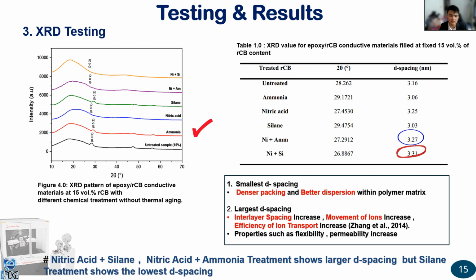Last, I want to discuss the result for the XRD testing. Based on the graph, you can see that the dual treatments, which are the nitric acid plus ammonia and the nitric acid plus silane treatment, show the largest d-spacing. A larger d-spacing means the interlayer spacing increases, the movement of the ions also increases so that the ions can be transferred more easily, and it helps to improve the dispersion of the conductive filler. It can also improve properties such as flexibility and permeability.